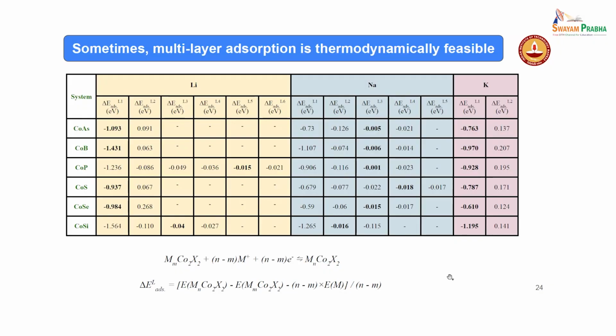There are a few ways that you need to omit. Some of these possibilities you have to omit. I will be telling each one of them. But please check one important point here: for the case of cobalt phosphide, you could load up to 5 layers. For cobalt silicide, you can load up to 3 layers. Whereas for sodium, the majority of them are only up to 3 layers. For potassium, only 1 layer. More than 1 layer, we were not able to load. How this would be affecting is what we will be seeing.